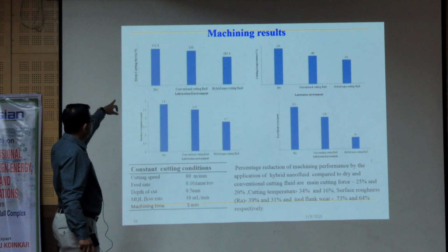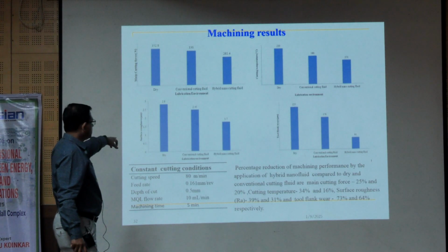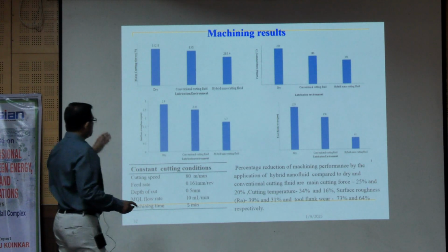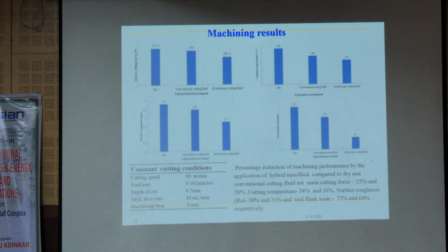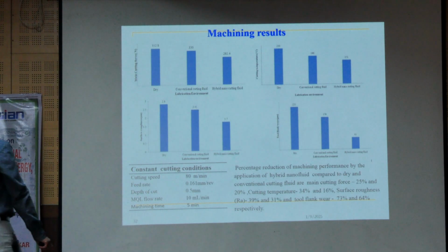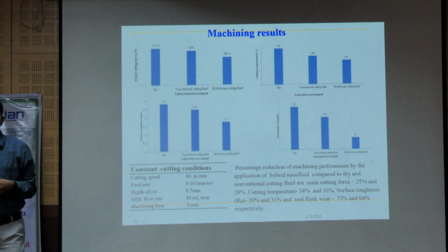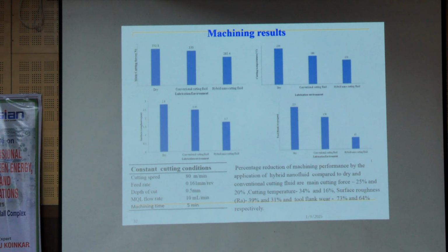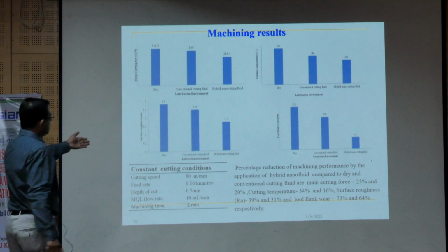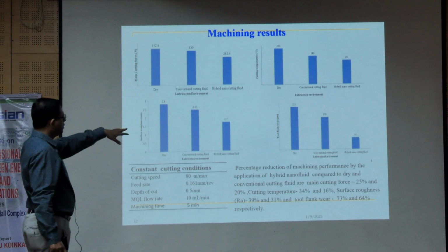So this is the cutting force, this is the cutting temperature, this is surface roughness, and this is tool flank wear. We got better performance in all 4 parameters compared to dry machining and conventional machining. And actually, more than the performance, the main motto of this work is biodegradability, right? We have to avoid pollution or environmental damage, but at the same time we have to check the performance also. That is why these are the performance tests. These are the cutting conditions we used, and then we got this improvement.